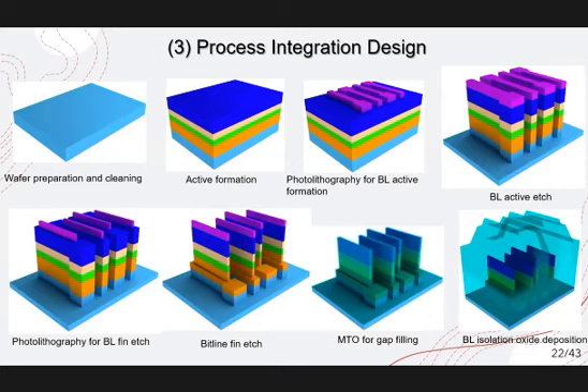So the second etch, the dry etch, should be stopped somewhere in the middle of the orange colored region, because that is the N-plus region that was formed on the p-type silicon substrate. So that is the place where the bitline contacts need to be formed, and then middle temperature oxidation can be performed for gap filling.